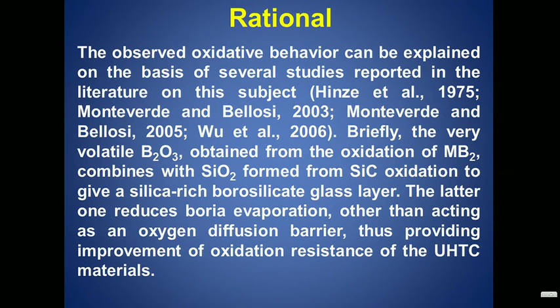So what's the rationale? That has been discussed in the literature quite well by several colleagues. Basically, the boria forms a silica-rich borosilicate glass layer, which acts as a diffusion barrier and also increases the oxidation resistance of these materials.